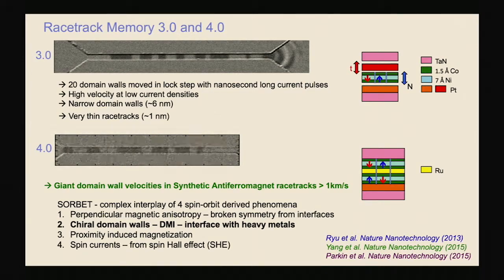So we can make one racetrack with perpendicularly magnetized domains, these Néel domain walls, and there will be an exact mirror image in the upper racetrack. So we can design it so that in net, aggregate, each domain consists of 2 domains in opposite directions with no net magnetization. And therefore there's no interaction, no dipole fields. And this is what makes racetrack possible. This is very interesting, I think. We call this a synthetic antiferromagnet.